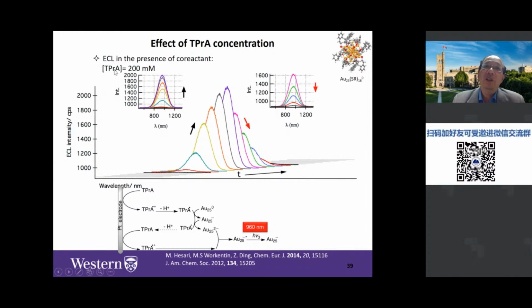Even more, we can also change the TPrA radical, TPrA concentration to 200 millimolar. And you can see here, because this is a strong reducing agent, it will reduce everything. That means it reduces the gold 25 0 in the solution to gold 25 2 minus. Okay, and then this gold 25 2 minus reacts with TPrA radical cation, then it will give you gold 25 minus excited state, which is at 960 nanometers. So in this slide, this gold 25 is also a kind of smarter material and will respond to the stimulus of the radical concentration of TPrA.